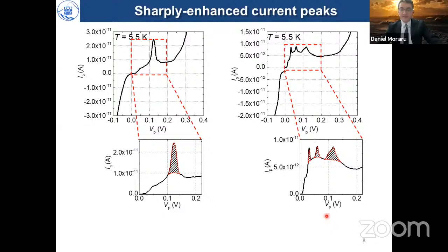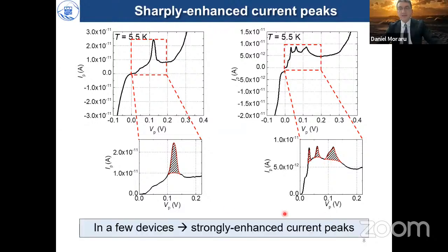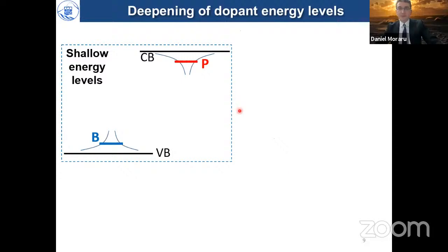So we believe that the strongly enhanced current peaks observed in several devices of this dimensionality are related to the donor and acceptor deep levels. Let me explain a bit more what this means. In large PN diodes, we expect to have boron acceptors and phosphorus donors in the same region of space, in the depletion layer. But they are both introducing shallow energy levels, about 45 millielectron volts inside the band gap.